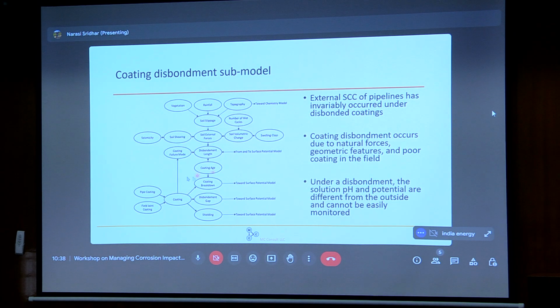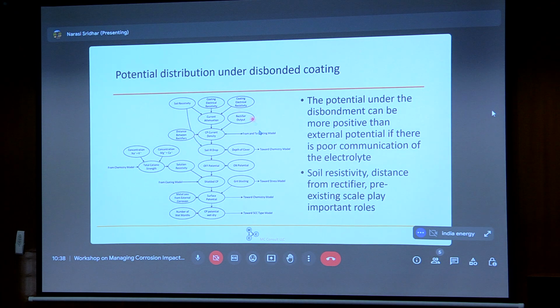So we go through this model, we can model this. For example, coating disbondment occurs because soil shears the coating, and that occurs because you have rainfall and you have a slope that moves the soil. But if you have a lot of vegetation, that prevents the soil from slipping. So you've got to capture all these things that the soil biologists and geologists study. And similarly, you have this potential distribution. So we have done a tremendous amount of modeling to calculate what happens inside the coating disbondment, and that's a function of soil chemistry. So we have to capture this as well.